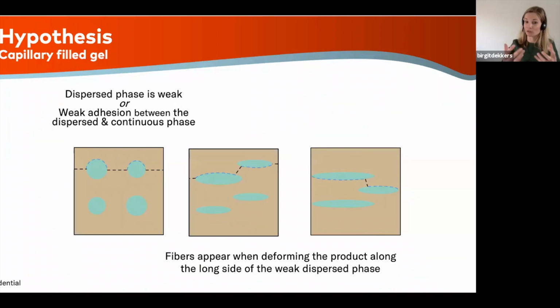And what you see macroscopically, when you deform these types of systems, the fibers are appearing when you deform the product along the long side of a weak dispersed phase. And basically the fibers that you see are the matrix, the continuous matrix in between the two dispersed phase droplets that are aligned in the shear flow direction. And this is actually what we see and what, when you start eating these types of products, you really feel as the fibers similar to meat. Because in meat, you also have these types of fiber structures and this anisotropy in your matrix.